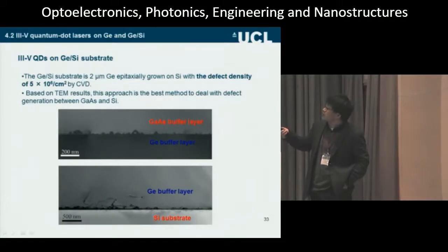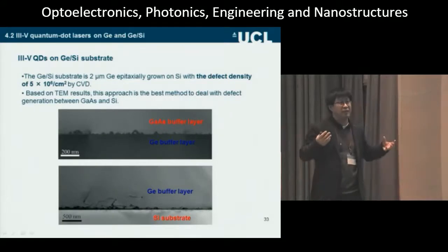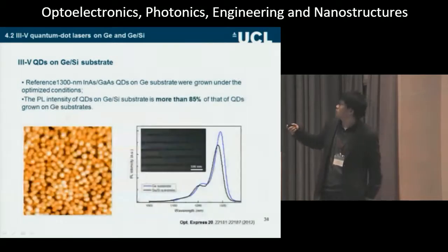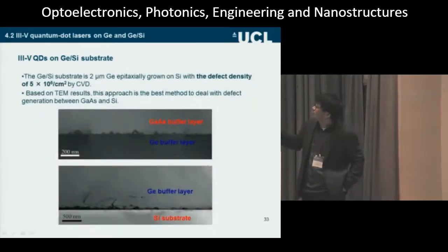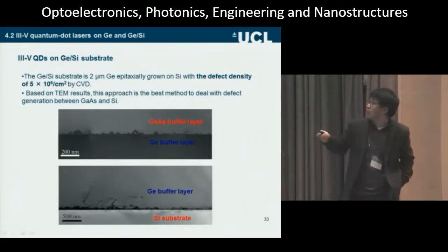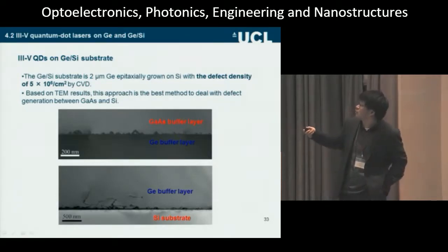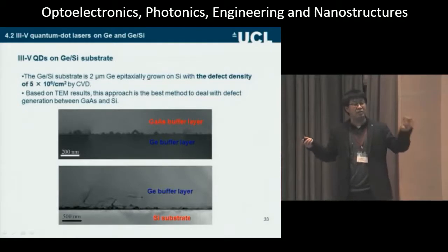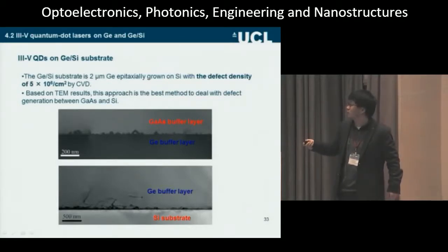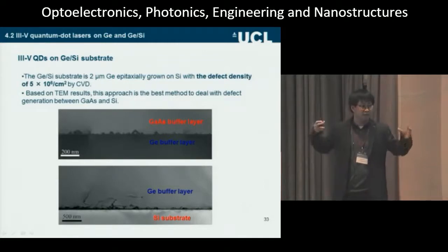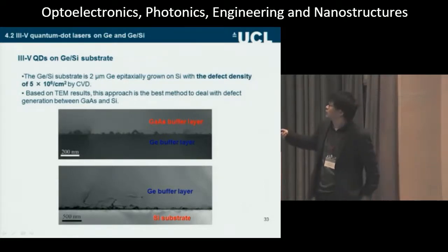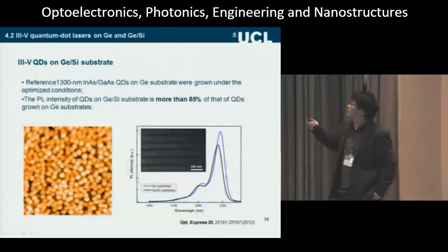So after that, the next step is, if you get a laser on germanium, can you put it on silicon? Because the goal is to put it on silicon chips. So we did get a 2 micron germanium buffer with a defect density of 5×10^6 by CVD from a friend. After that, we use the same approach, put the gallium arsenide on the silicon. You can see, guys, actually germanium buffer on silicon is very mature now. If you grow a germanium buffer, the defects are well confined in the interface. And also, we have a gallium arsenide buffer and the germanium buffer also confine defects very well. After that, we grow quantum dots.